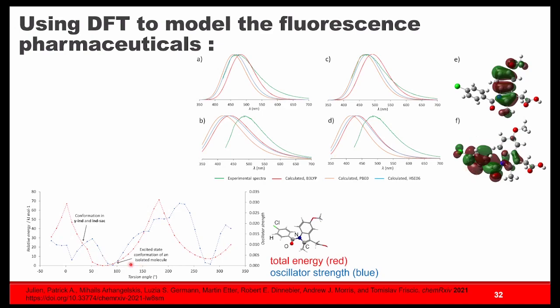And what we actually found is that if you look at this, near the bottom here, in terms of total energy, there's relatively low oscillator strength, so we wouldn't expect things to be very fluorescent, which seems to be the case, for example, in solution. You'd expect most of your molecules to have this type of conformation that's going to be non-emissive. However, in the solid state, if you look at this angle in the crystal structures, we're here. And so all of a sudden, we're higher in the total energy of the bond itself, but that's being stabilized by the crystal structure.